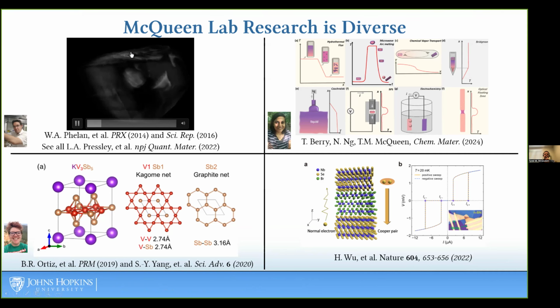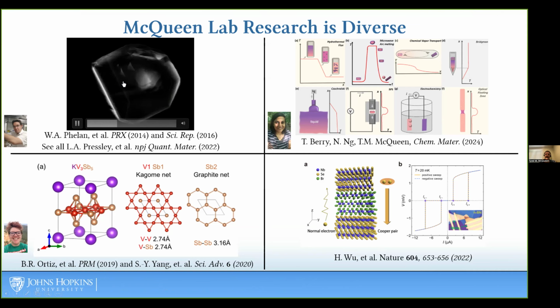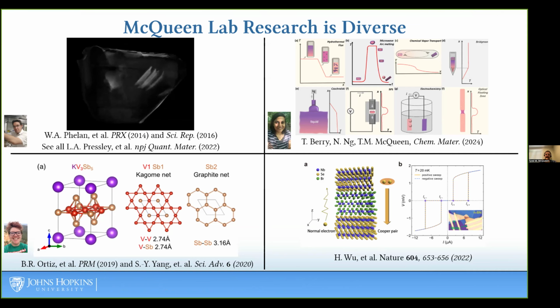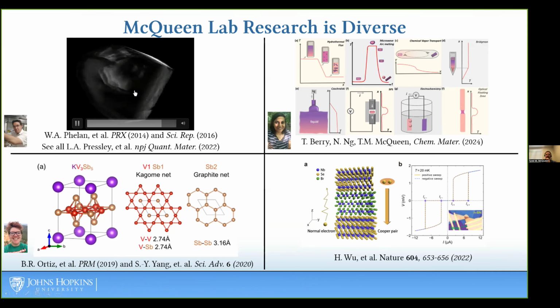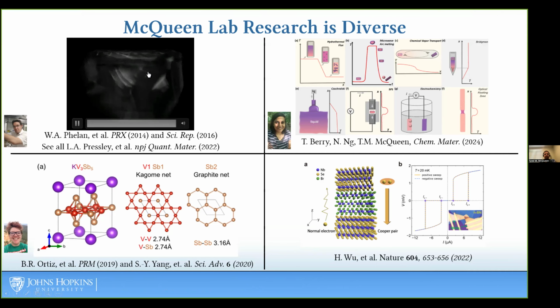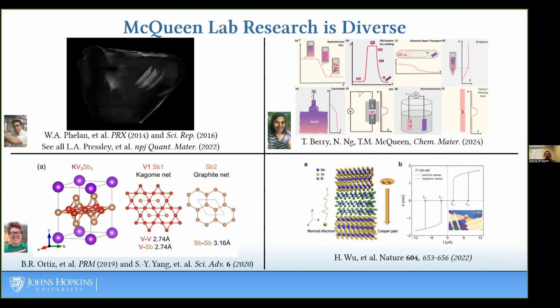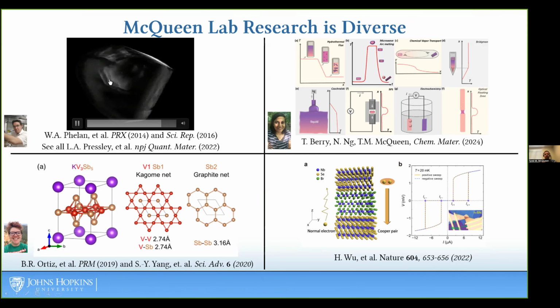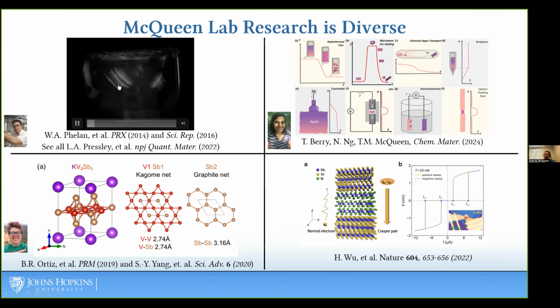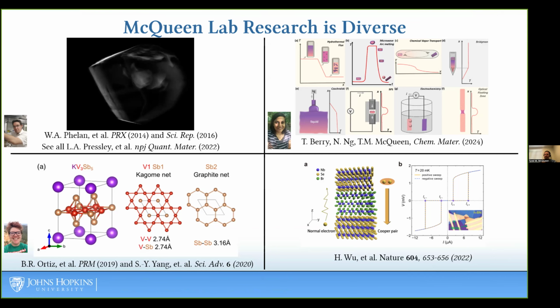So in the upper left here, this is a piece of a crystal of a material called samarium hexaboride, which is a topological Kondo insulator. What I like about this is using a technique from materials science called microcomputed tomography to actually look inside this flux-grown single crystal and see if there are inclusions of the aluminum flux. And indeed, you can, and the contrast has been adjusted to highlight low Z aluminum inclusions. You can see very nicely that there are aluminum inclusions in this. But even more importantly, you can see that they're not oriented randomly, that, in fact, they have very distinct orientations.